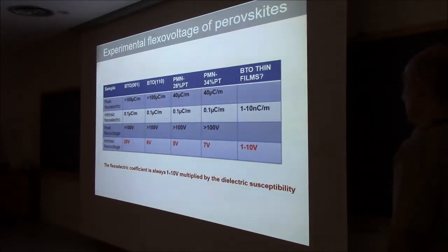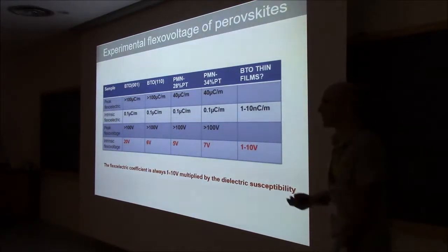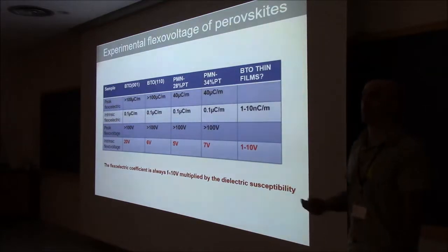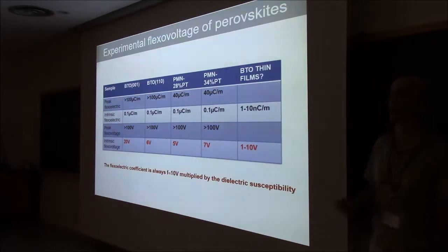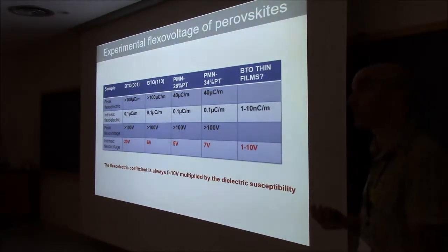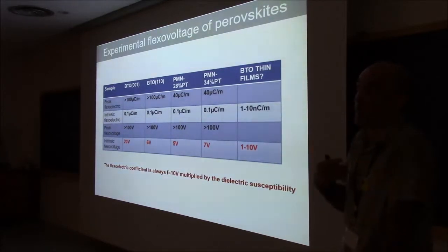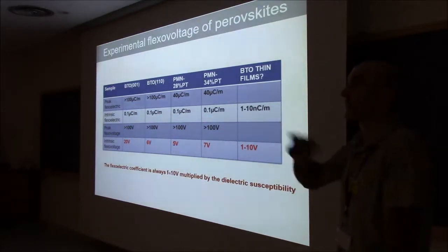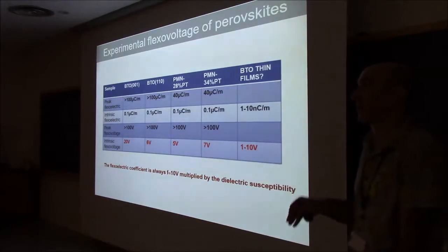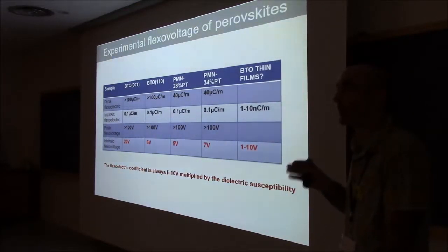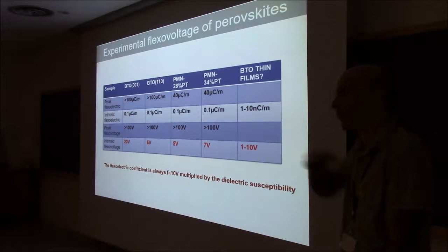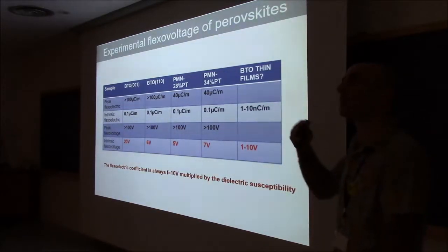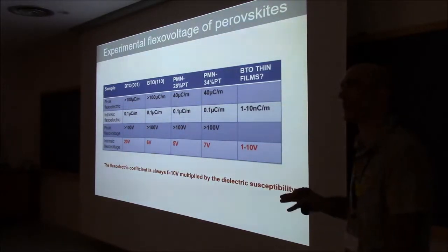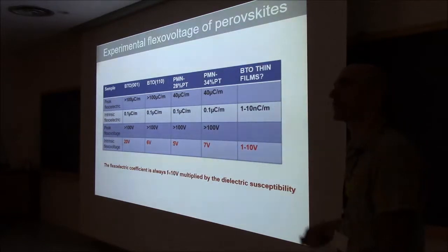Yeah. So if you have a material for which you expect that there will be flexoelectric effects, and you have no idea as to how to quantify them, your first guess, or my first guess, would be 10 volts times the dielectric constant. Okay? And that will probably give you a good approximation. So if you don't know what the flexoelectricity of your material is, that guess for me would be quite acceptable. 10 volts times the dielectric susceptibility.